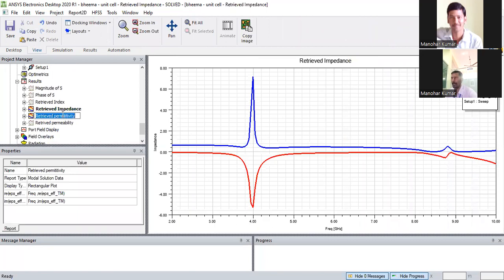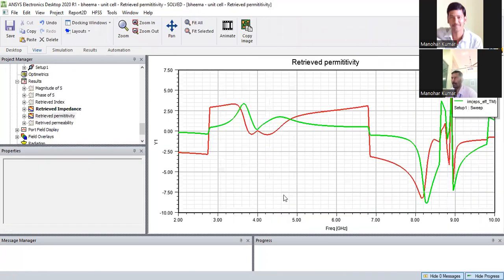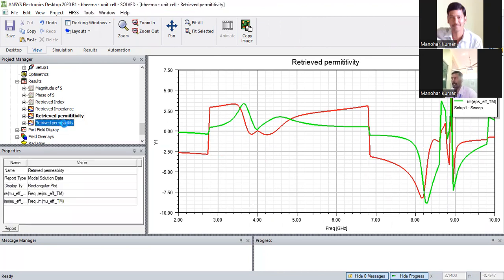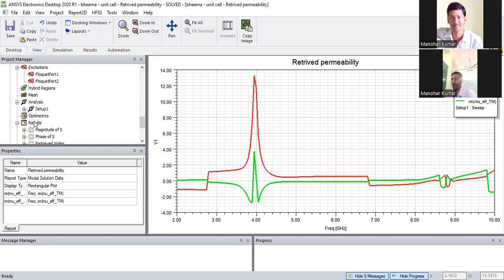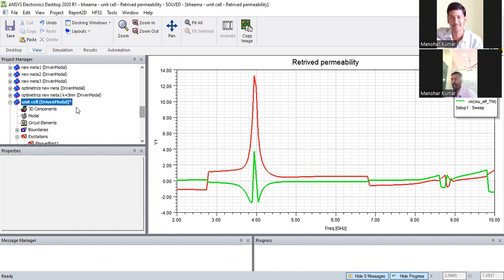If I see the permittivity of the material — in the 7 to 9 GHz range, it has negative epsilon and negative mu. You can see the green curve and red curve. Looking at the permeability, at some point the real value becomes negative — in this region and from 8 to 9 GHz also, it has negative values. Some metamaterials have only epsilon negative with permeability positive, or permeability negative with epsilon positive — those are single negative metamaterial structures. For this structure, I got these results.